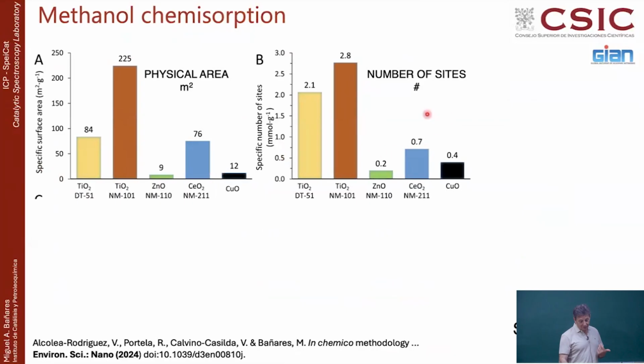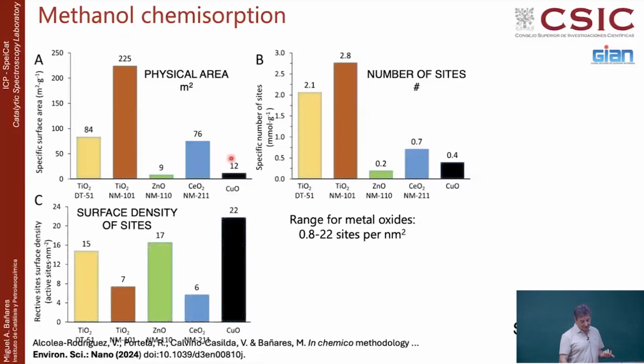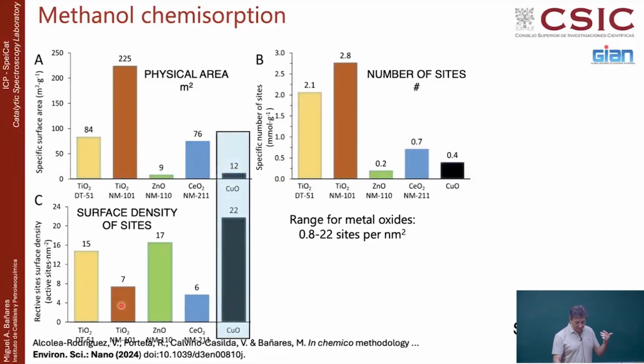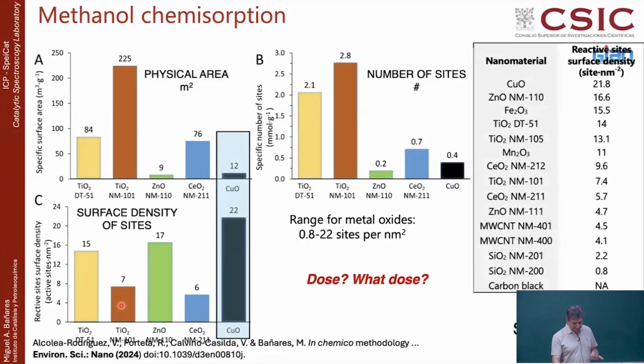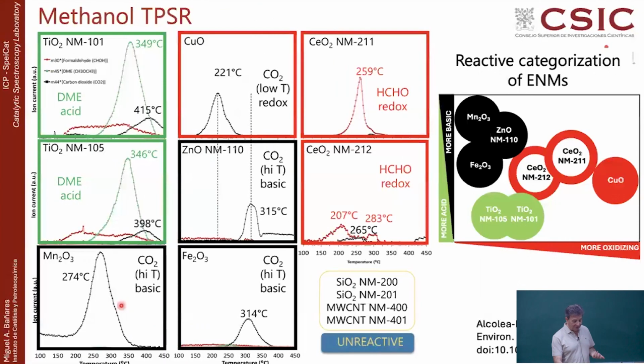But when you normalize the number of sites per gram by the number of square meters per gram, you see that samples with very low area have many sites per square nanometer, like this one, or like that one. Sometimes materials with a very high area don't have so many sites per square nanometer. So the surface per se was not a critical factor. And when they are talking about the dose, which dose? They like to talk about grams, they like to talk about square meters, but shouldn't we talk about the number of sites if you want to get an insight on toxicity? So we were doing that.